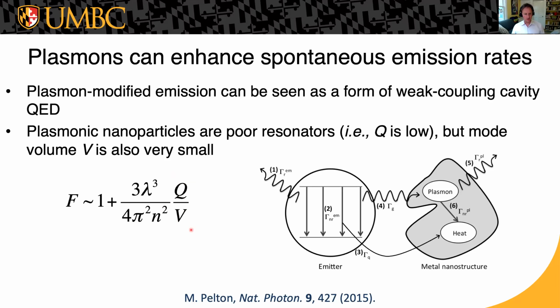we have to be careful about things like defining mode volumes for open cavities, and there have been a lot of very good talks in this series about the proper theory for describing quantum electrodynamics in these sorts of systems. But my theory is not nearly as sophisticated as all of that. Just as a heuristic, we can still think of the mode volume, the confinement volume around these plasmonic nanocavities, as being no longer restricted by diffraction, because you're coupling to material excitations. And now you can get Purcell factors that are much higher than you can get in photonic cavities, even though the quality factor of these plasmonic cavities is quite low. Plasmon lifetimes inside these cavities are in the 10 to 100 femtosecond range, given quality factors on the order of 10. But nonetheless, the highest Purcell factors people have observed are in plasmonic systems.